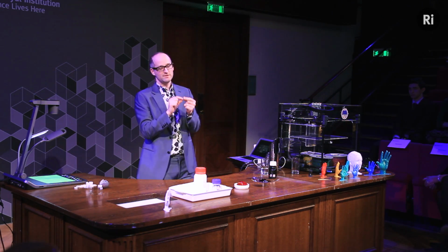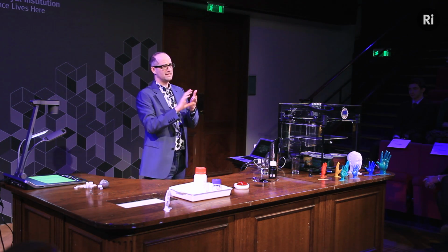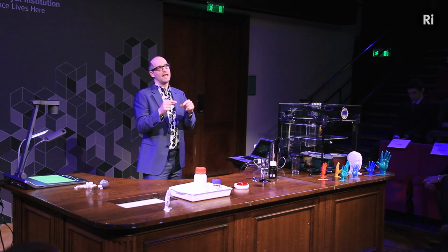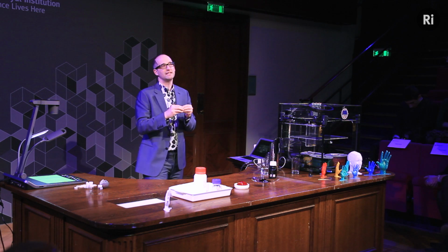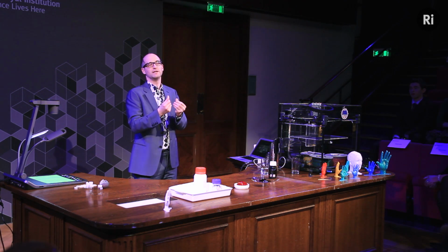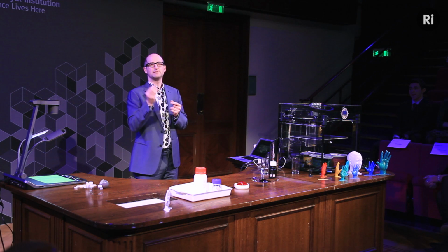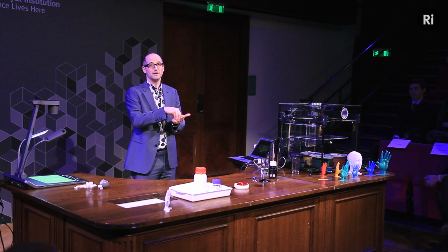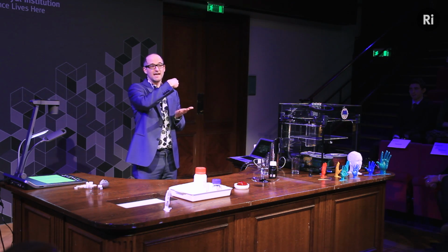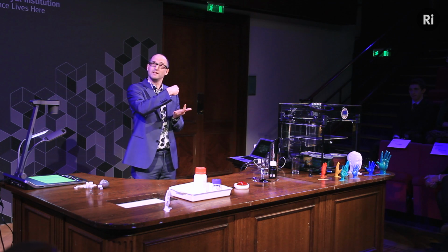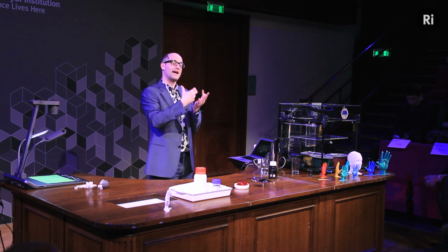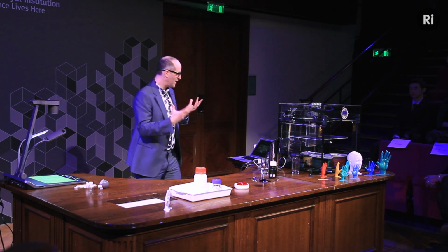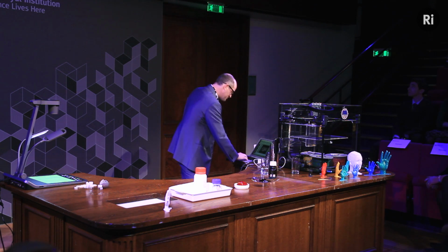And you add small amounts of alloy, silver, copper, zinc, and you get a reaction between those metals, and it will turn into another metal that's still ductile, still hard, but actually is solid. And that reaction doesn't take very long. It takes about 30 seconds if you get it right. So you can make up something that's a liquid, put it into the cavity, and in about 30 seconds' time, it's hard and it's a solid. It will remain solid for the rest of your life and is very hard and very durable. And without that material, my God, how much pain would we all have suffered over the years?